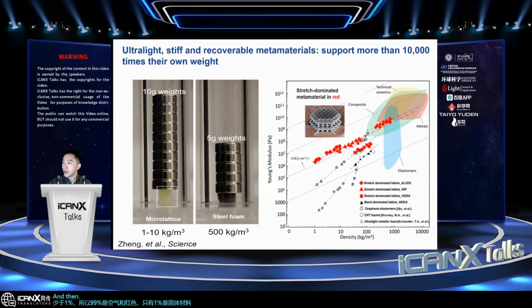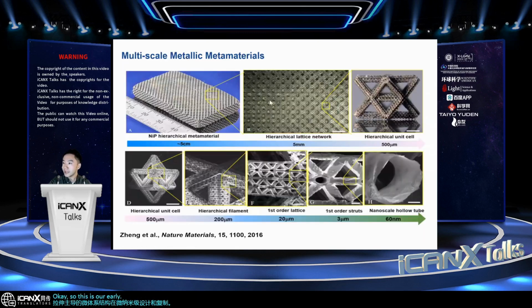And then we show that at much lower density. This is a density almost similar to carbon aerogel, but you can achieve more than 4 orders of magnitude higher stiffness and strength at ultra low density. This is really attributed to the stretch dominated microarchitecture being designed and replicated at micro and nanometer length scale. Okay, so this is our earlier work, and then we followed up these metamaterial concepts to larger length scales and to different materials.